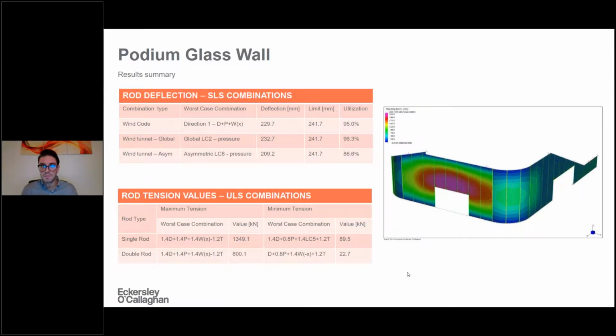And in terms of maximum or minimum axial load in the tension rod, we had a peak of almost 1400 kilonewton for the full light single rod and 800 kilonewton for the full light double rod, while the shorter rod under positive temperature and other scenarios which were aimed to minimize the tension, was seeing a value of axial load still below zero. So no rod was going in compression, but clearly with a much smaller margin of value. So you can see here from like 89.5 to 22.7 kilonewton for these very specific load case scenarios.